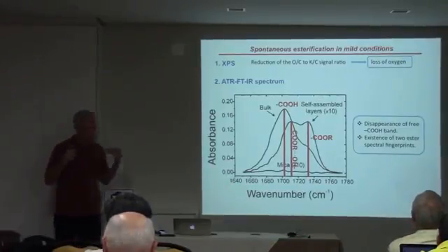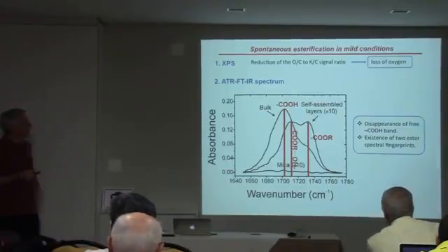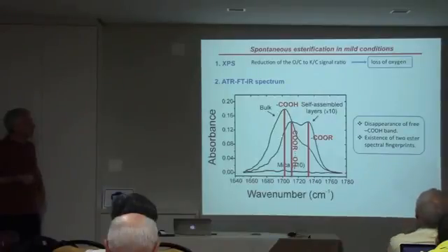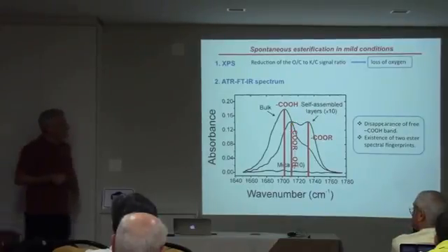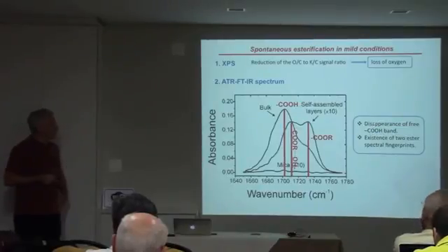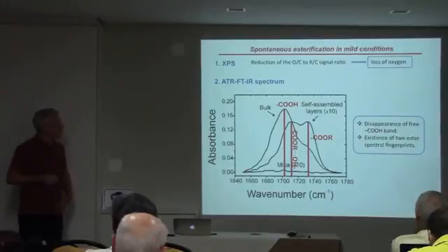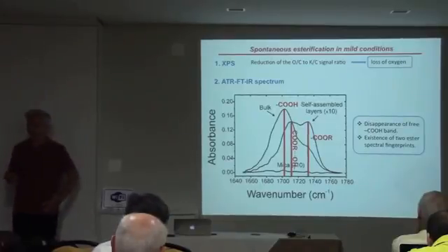Looking back at the monomers, if we take a spectrum from carboxylic groups, we would expect this spectrum. However, what we find here is this other one. This other one doesn't have the signal from the carboxylic group anymore, and there are two new spectral fingerprints corresponding to the formation of ester.